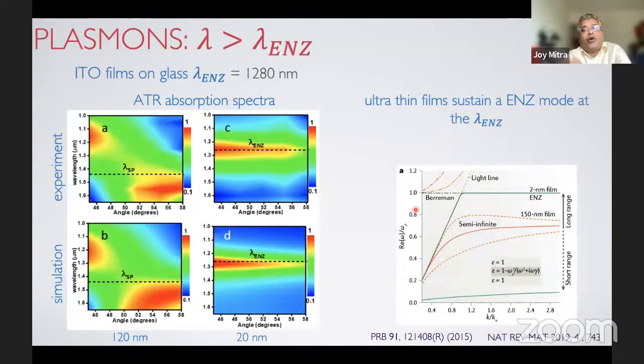Okay, so what do you do with it? Since we entered the field in terms of plasmonics, we first went on to discuss optical surface plasmons being excited in these oxide films in the near IR regime. The first thing we did was take a 120 nanometer film of ITO and try to excite the plasmons at wavelengths beyond lambda ENZ, where it is optically a metal. These are ATR absorption spectra, excited through a prism. Experimentally, we saw that indeed you have large absorption, which pretty much matches the simulated plasmonic response of these 120 nanometer thin films.